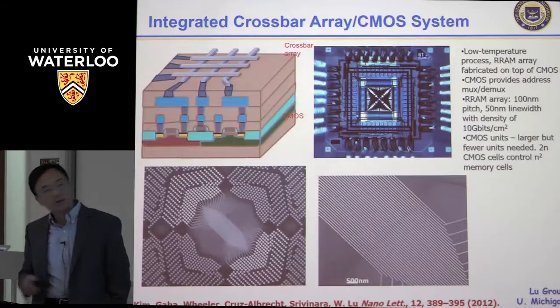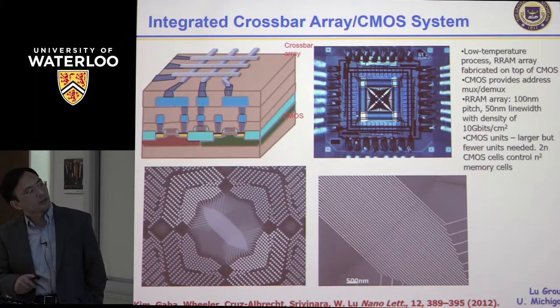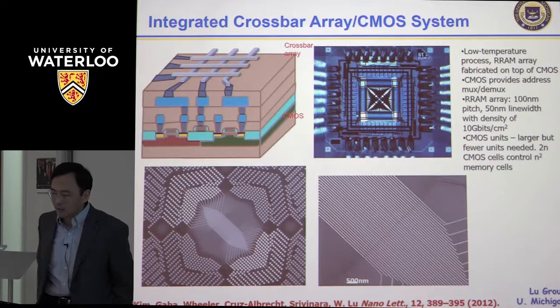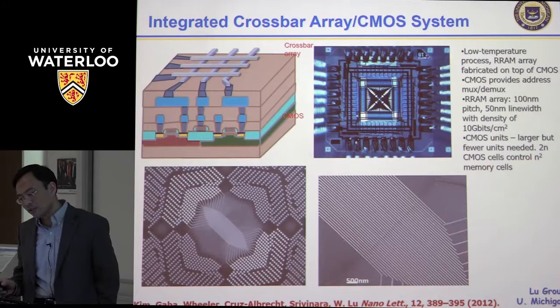You can also integrate them on silicon. So this is an earlier project sponsored by DARPA. We built this crossbar array on top of a silicon circuit. These are not integrated at the pad level. These are directly integrated through the CMOS vias. So they are very high density. You can actually see them here. They are very high density local vias. So we can directly integrate the device on top because the device fabrication doesn't require a high temperature process. All the processes are low temperature, so the CMOS underneath is not affected by the RRAM array fabrication.